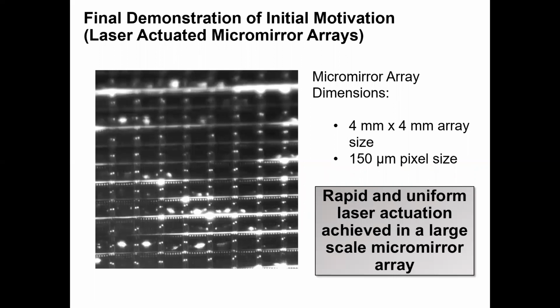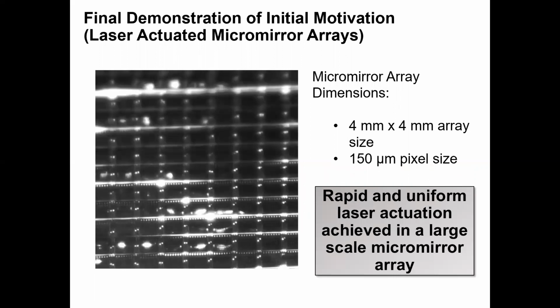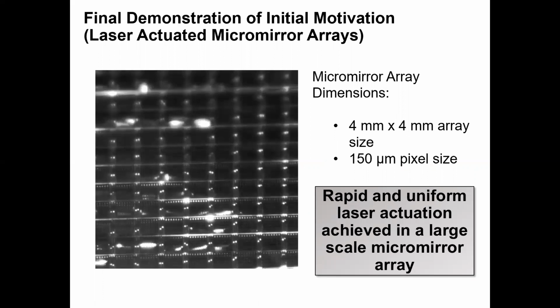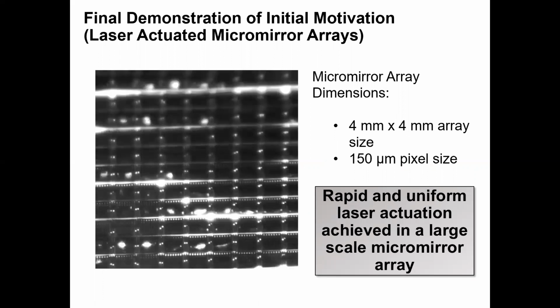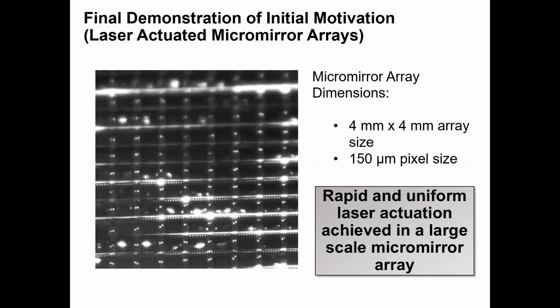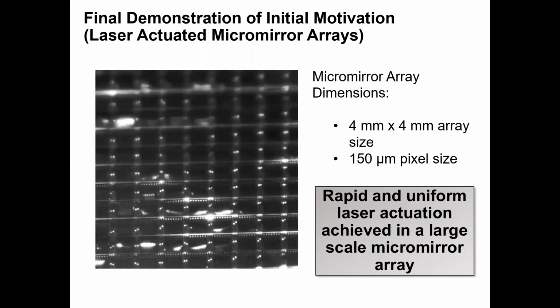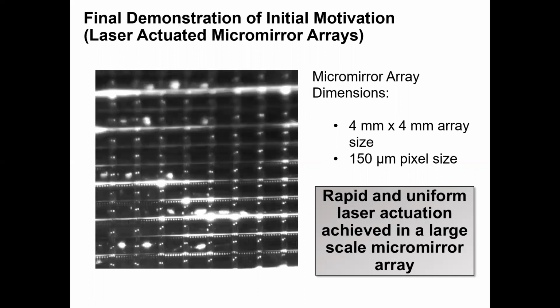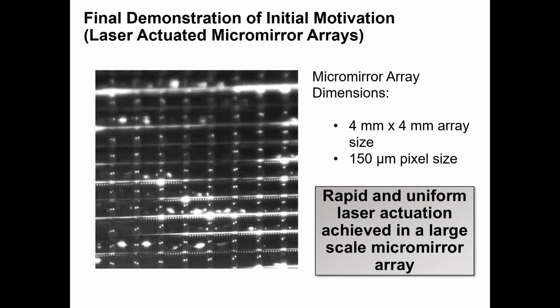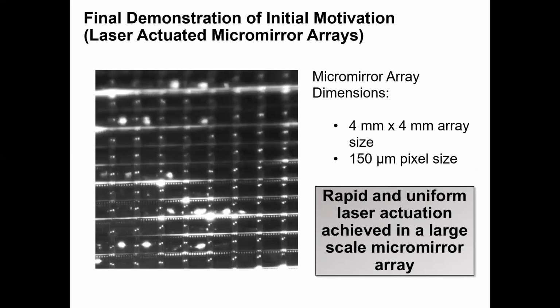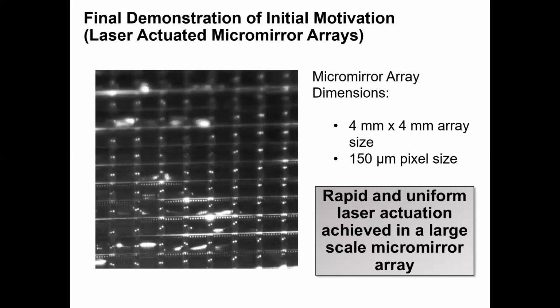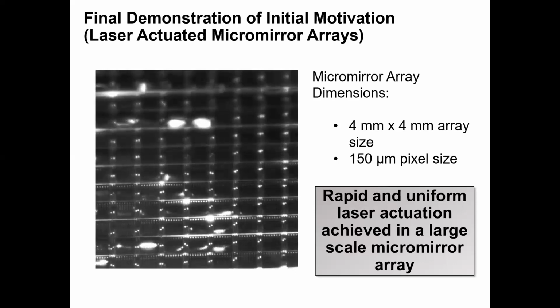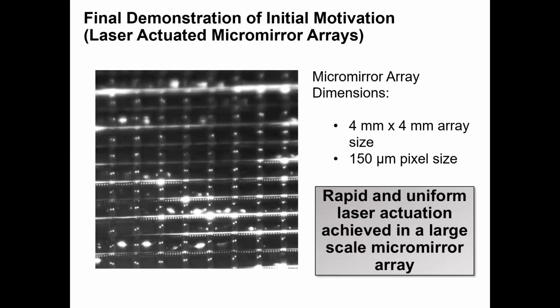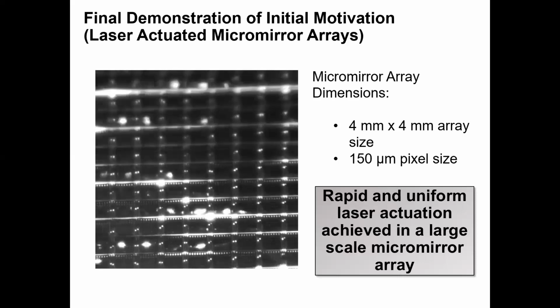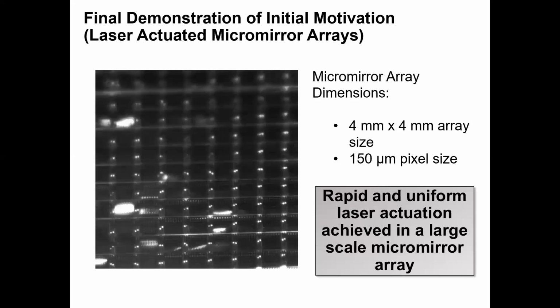So as a final demonstration of this initial motivation, I was able to build these large scale micromirror arrays on a silicon wafer. The dimensions of the active array here are 4 millimeter by 4 millimeter with 150 micron pixel size. This rapid laser actuation was achieved using a diffuse laser beam in the visible band. And because the beam was diffusely focused over the entire array, each of the pixels actuated more or less simultaneously. When the laser was turned off, the actuation was shown to be reversible. So overall, the two-way shape memory effect was achieved for a few cycles on these mirrors.